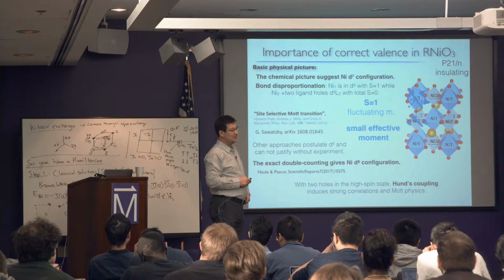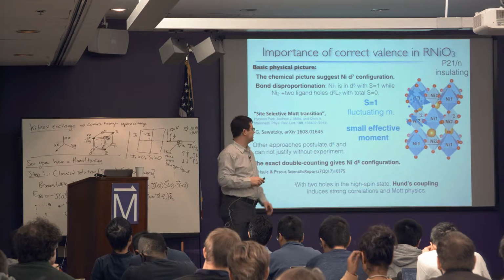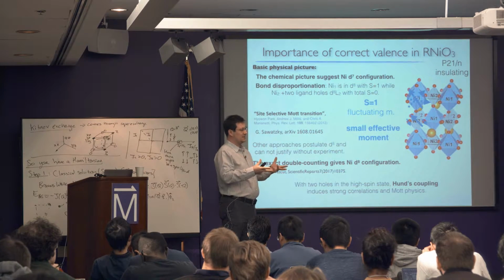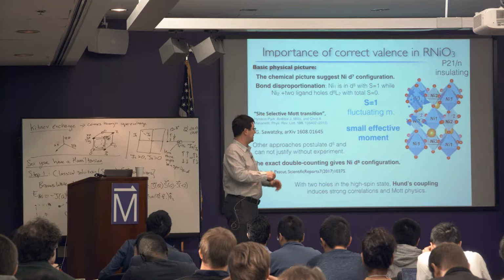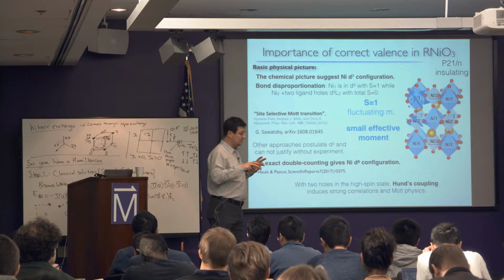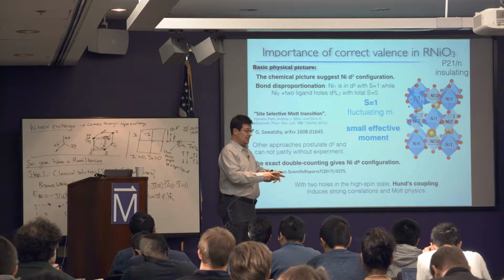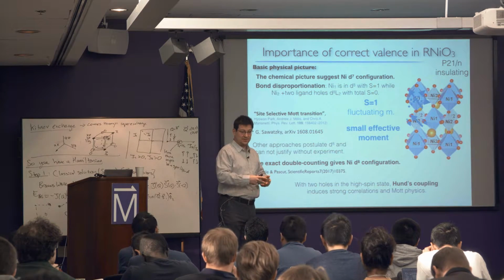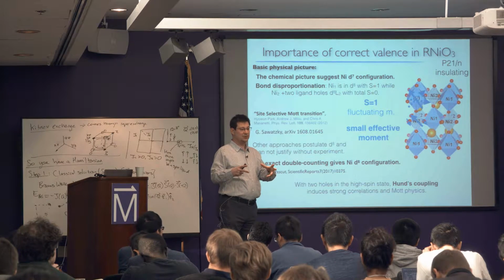was the rare earth nickelates, in which there is a very interesting type of Mott transition, where in the paramagnetic state at high temperature, you have a metal where the nickel octahedra are of the same size, but then when you go to low temperature, one octahedra, which you call nickel 1, expands a lot, and every second octahedra contracts a lot. And the one that expands turns out to become Mott insulating.